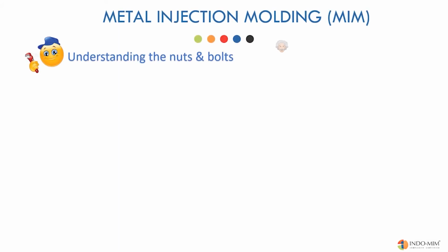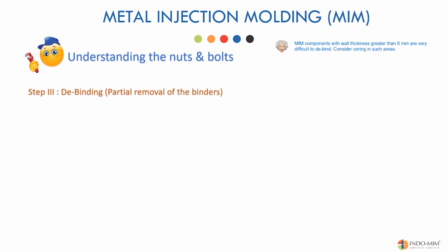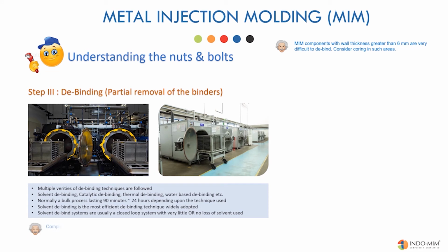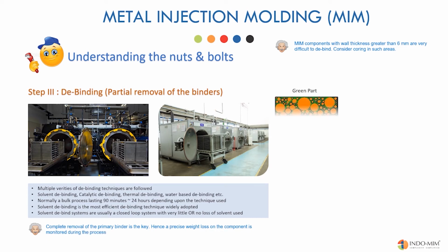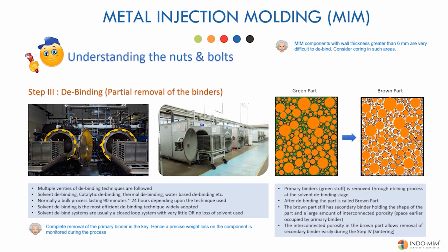Once the feedstock is molded into shape, we don't need the plastic binders on the parts. The process of partially removing the binders is called debinding. The MIM binders are broadly categorized into 2 categories, primary and secondary binders. At debinding stage, we remove the primary binders through a solvent extraction method. Debinding technique depends on the binder recipe used. Some MIM vendors use catalytic debinding and some use thermal process. Solvent-based process is the most economical and efficient method.